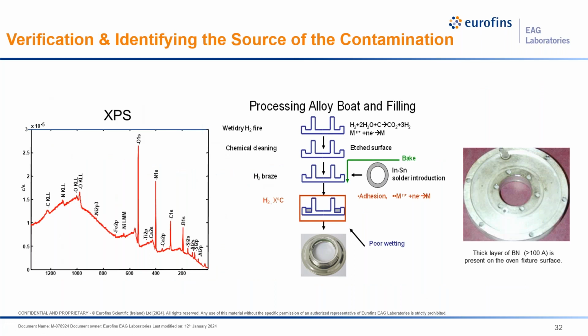So that didn't really fit into any of the possible scenarios for the client's reasons for the wetting problem that they were experiencing. So we decided to run another secondary technique, XPS, which I'll talk about in a little bit, just to confirm that there was indeed boron, carbon, nitrogen, and again, because of the similar sampling depths, we see some of the Kovar peaks present. So once confirmed that this was indeed a boron nitrogen carbon issue, we worked with the client to go through the process and started pulling samples at various points during the process steps to identify the point at which the contaminant was introduced. And then from there, we're able to identify the source.